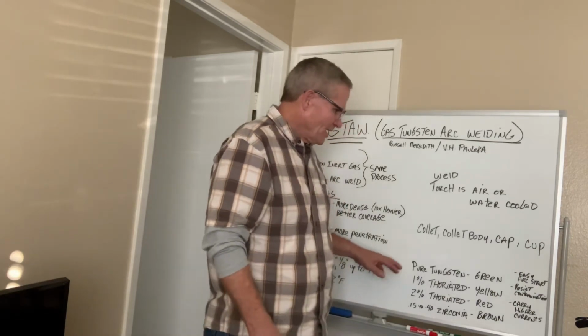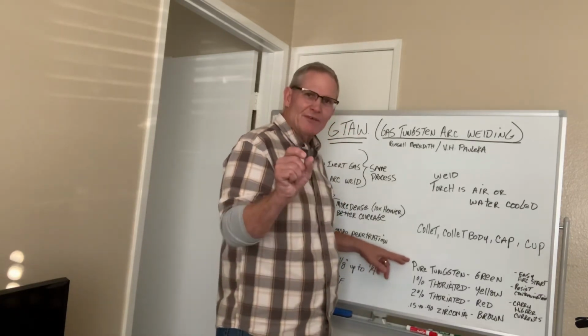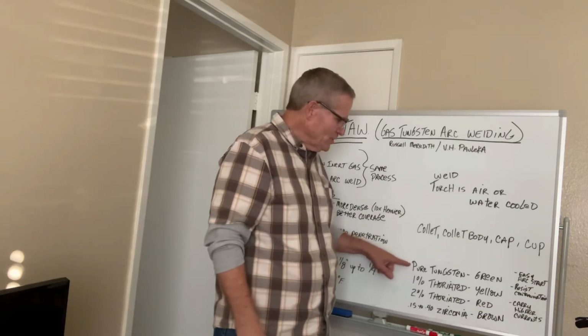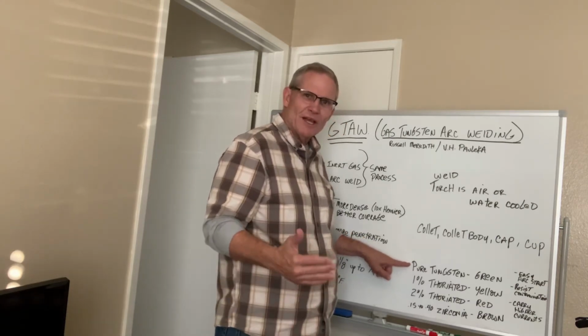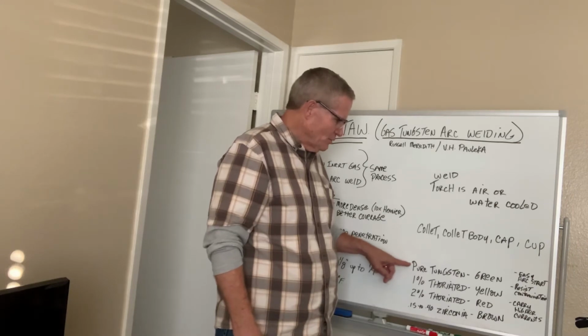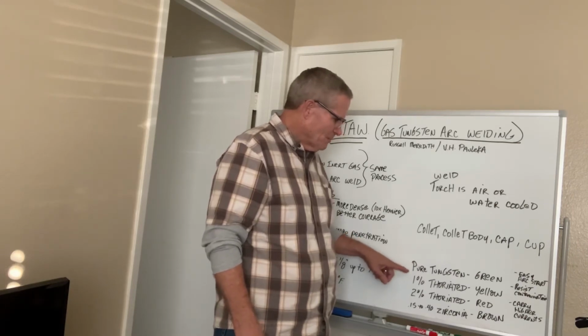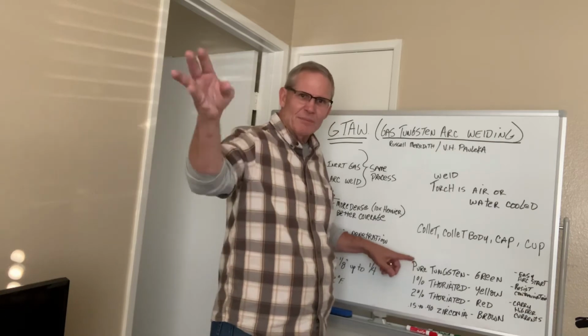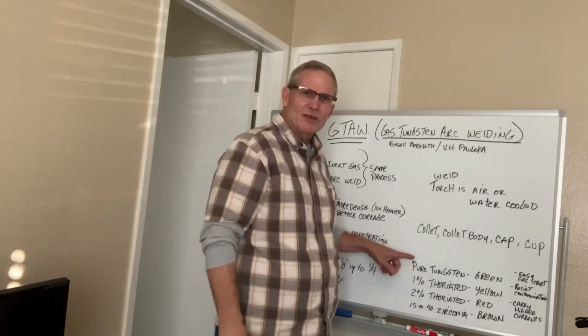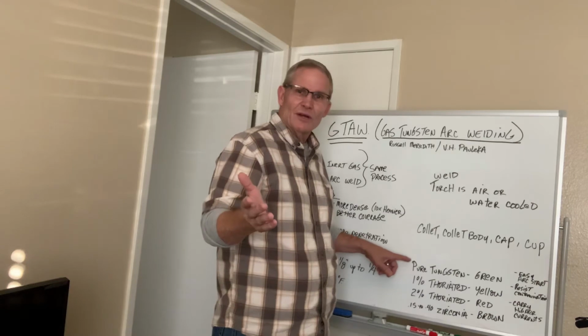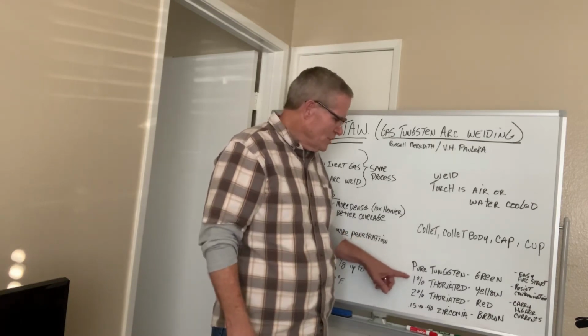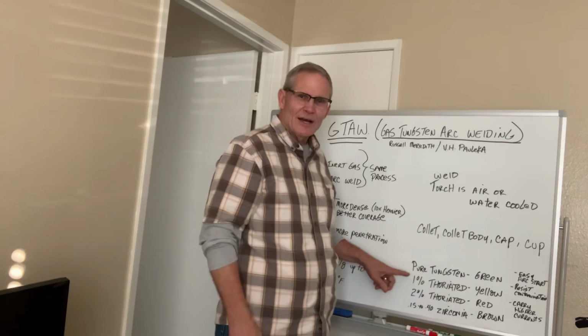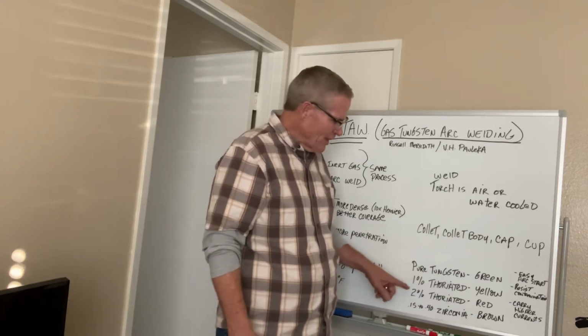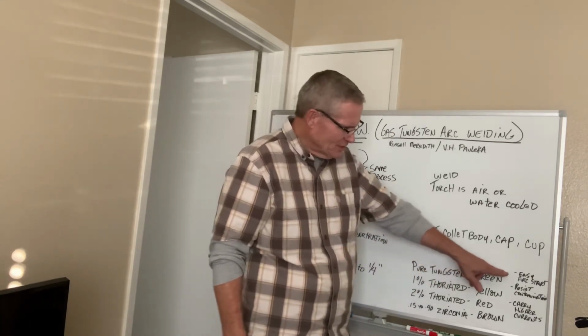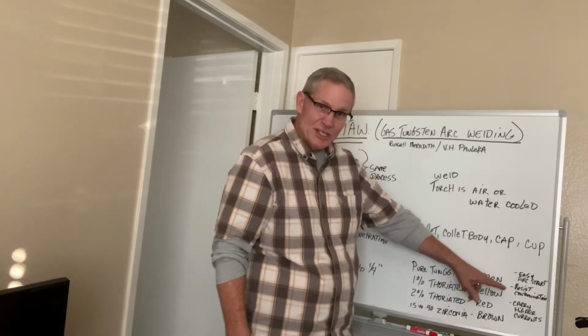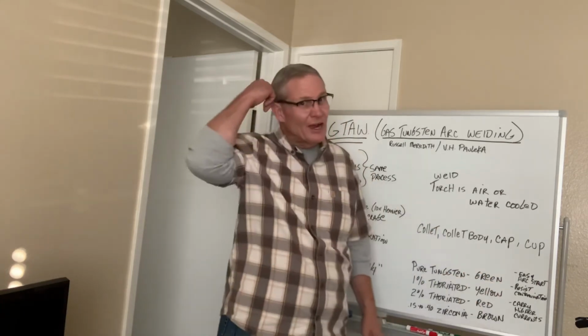With tungsten, you can get pure tungsten. The end of it is green. Typically we use this for aluminum. So if you're welding aluminum on AC current, we use the green, the pure tungsten. But if you're welding all these other metals, the Inconels and the Monels and the stainless steels and regular carbon steel, we usually get into an alloyed tungsten. The reason they alloy them is because they're easier to start the arc, they resist contamination, and you can carry higher currents with them.